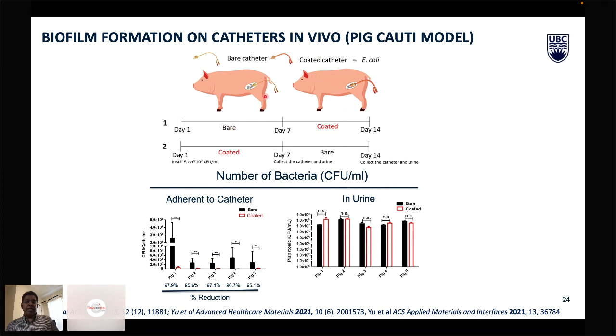You could see here a pig catheter where the modification has been adapted to a large catheter size, and you could see that almost 95 to 97% prevention of biofilm formation is achieved here. So we place a catheter, instill the bacteria, wait for 7 days, remove the catheter and analyze the bacteria on the surface.